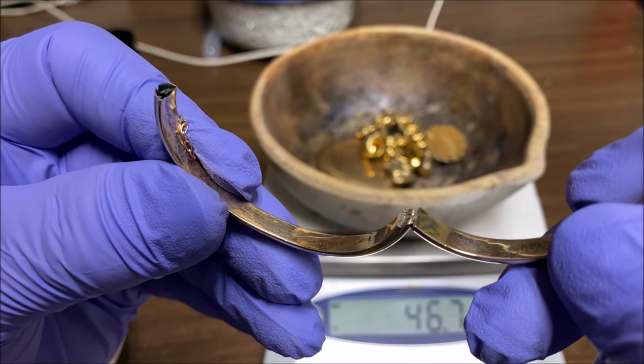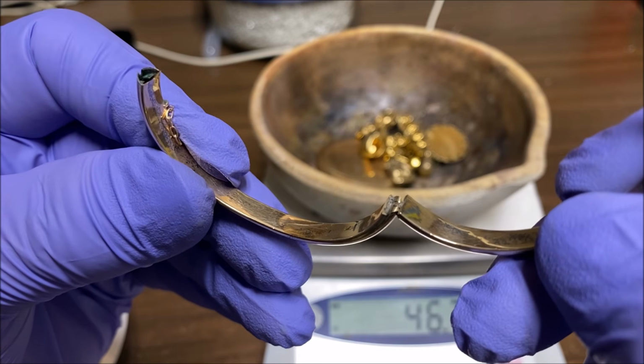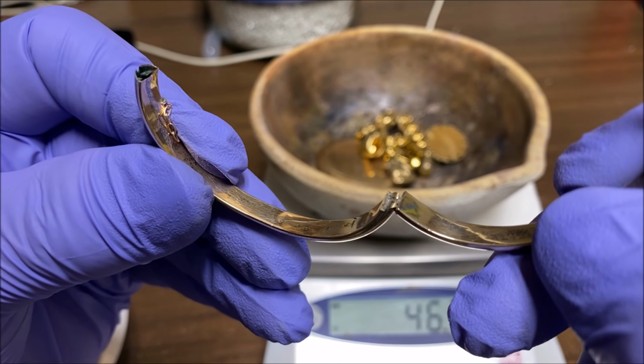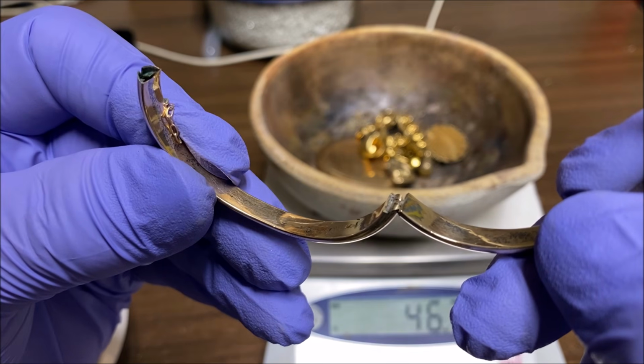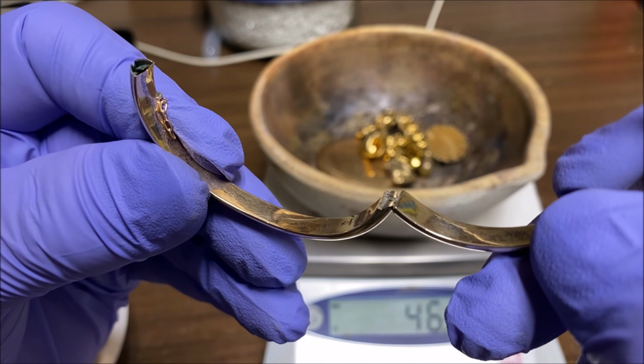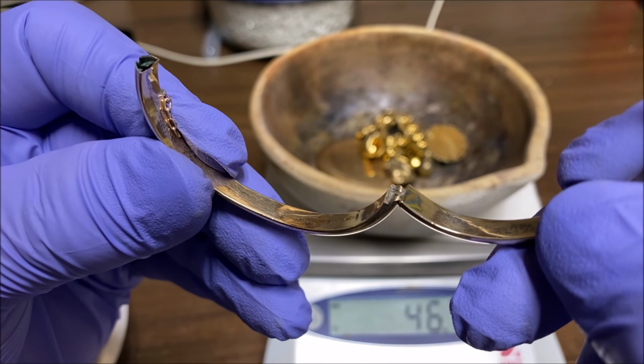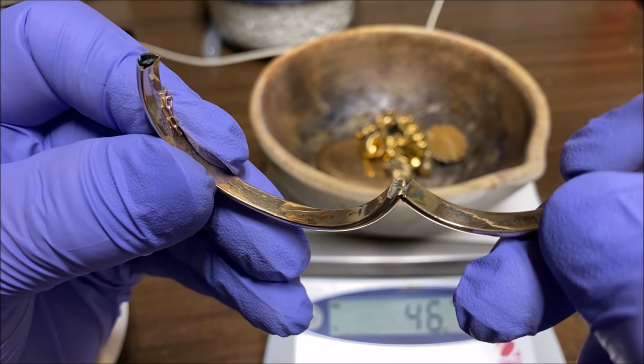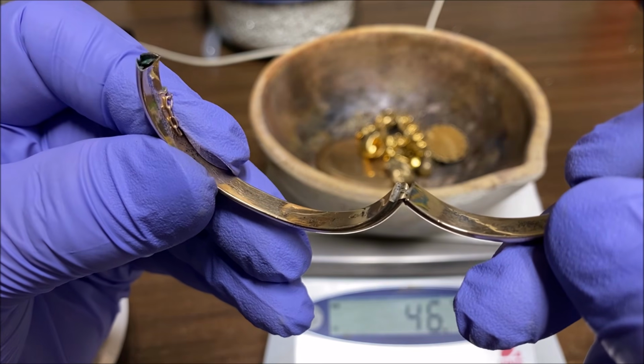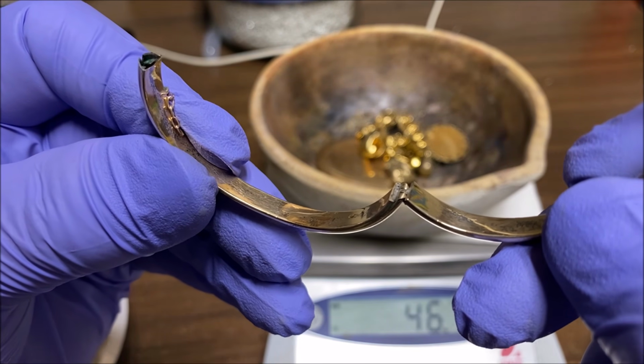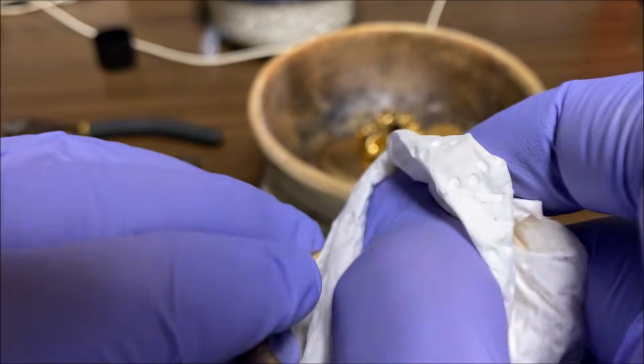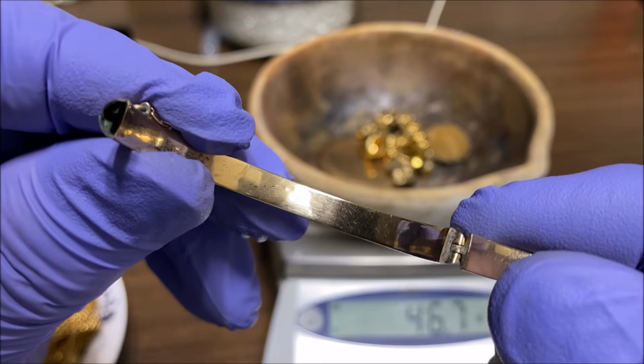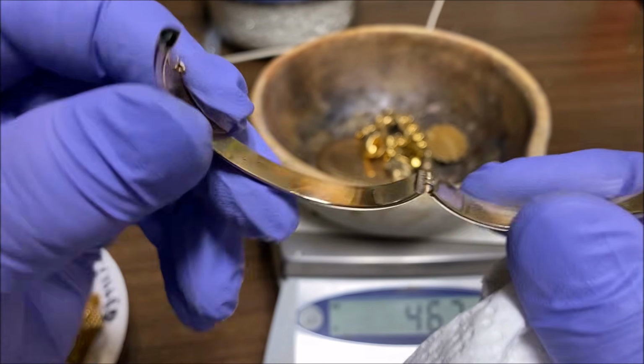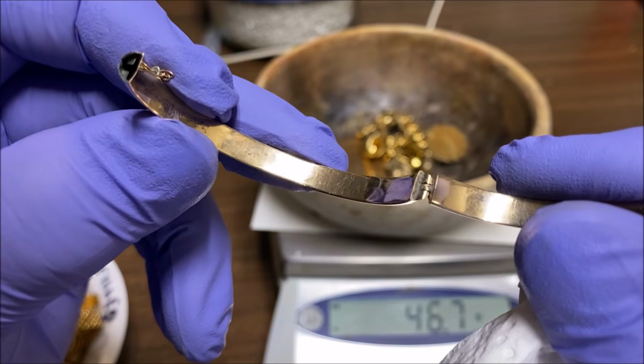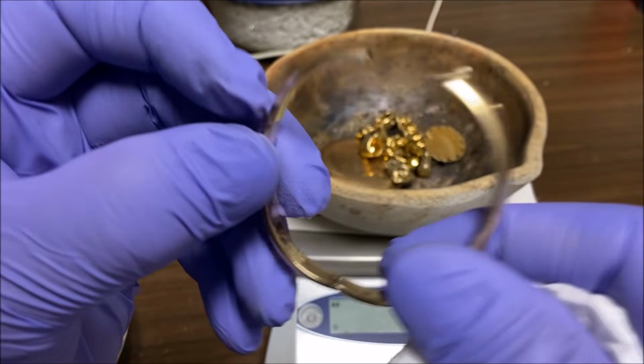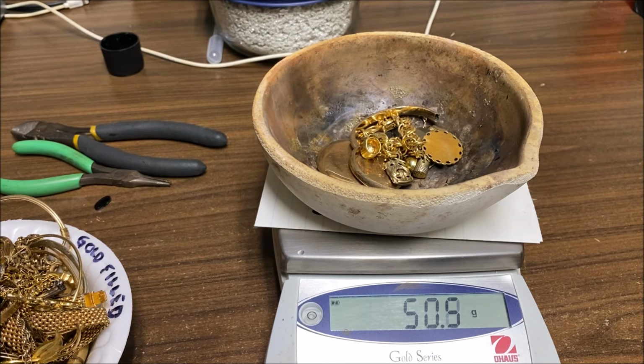If this was gold-plated, that drop of acid would have turned green, started bubbling, and stink to high heaven almost immediately as soon as I put it on, because gold-plated material is just a few microns of thinly coated gold over a junk metal. And this piece has not reacted, so that tells me that there's karat gold over brass. This is a gold-filled piece. I wiped the acid away. There's no mark where that acid was sitting. That verifies that this is a thick coating of karat gold over brass. This is gold-filled, and I can add it to this batch of scrap.